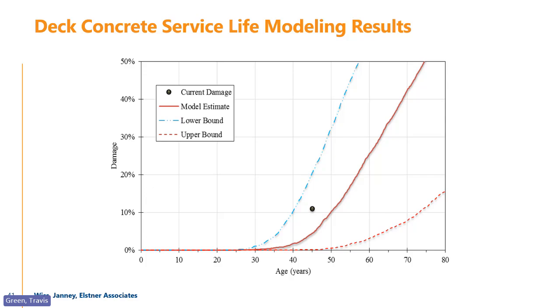So this is what we end up with, right? We don't always use a lower bound and an upper bound, but in this case, we can just look at the model. We look at the current damage, that's that black dot there, and then we're predicting when we see, let's say, 20% surface damage, right? So we would say, hey, listen, we're at 45 years, at 55 years, if things stay generally the same, or 58 years, you're going to be in that 20% damage range. Now if we say, listen, we have lower cover and higher diffusion coefficients, or higher cover and lower diffusion coefficients, it changes. But consider this a mean type estimate. What we're saying to them is, at 55 or 58 years, you're going to have a good bit of damage, and you're really going to have to be considering replacement or significant renovation of that element.